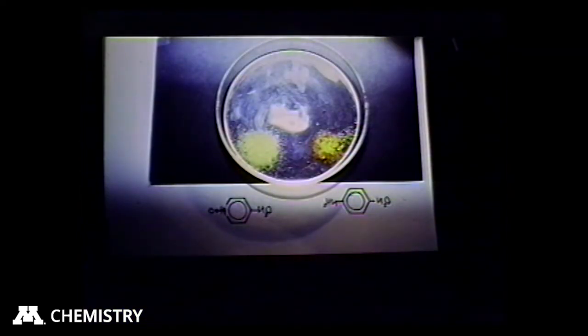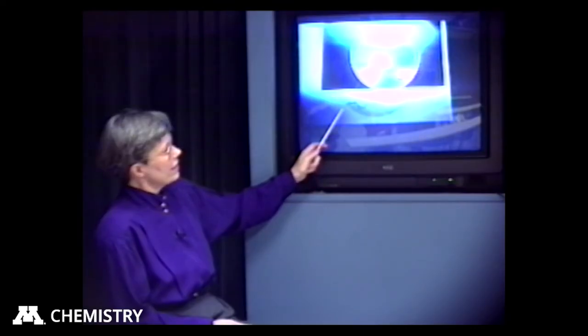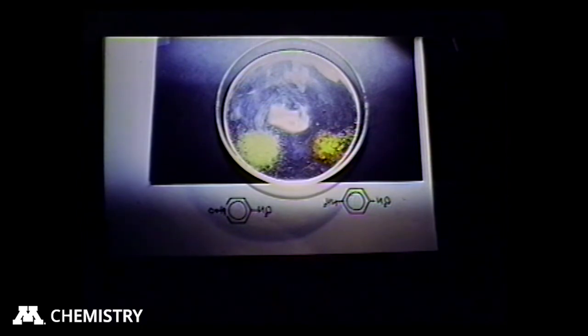Now, you don't even have to grind some of these samples. What I have here, although the structures are backwards, in the Petri dish on the left is paranitropyridine N-oxide. And on the right, I have paranitroaniline, which is yellow. And around the edges, you can see something that's red. The red color develops in this Petri dish if you simply cover it and let it sit on the benchtop for a while. What happens is that paranitropyridine N-oxide, which has a reasonable vapor pressure, simply sublimes and finds its way over to the paranitroaniline, and when it does so, co-crystals form. So this is a gas-solid reaction.